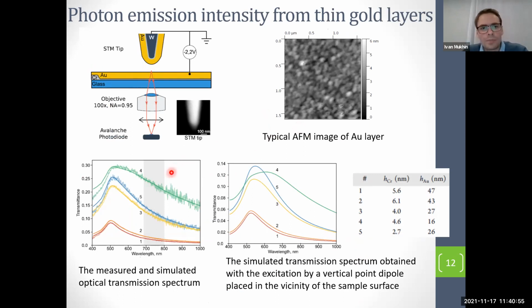We have five different substrates covered with gold thermally evaporated with different technological parameters, and the thickness of these structures was estimated through an optical experiment, a transmission experiment with a plane wave. We use a chromium layer to increase the adhesion of the gold layer to the substrate. Do you remember, in my previous part I mentioned that actually we don't have a plane wave. Tunnel current can be considered a single-point optical dipole located under the STM tip. So is it correct to use this experimental result to describe a real situation?